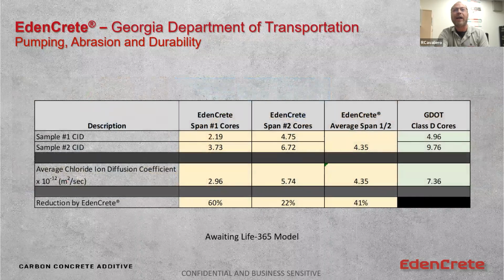We actually went back out, and I just went out with a group a couple months ago, and we pulled cores. We ran that chloride ion diffusion test. And what we're seeing is that with EdenCrete, we had 2 spans, and we have an average of 4.35, but ultimately, we see that 1 span did really well and has a 60% improvement over the reference, which is the GDOT Class D. The second one has a 22% improvement. So when we average that, we have a 41% improvement in permeability over the reference for a bridge deck that's reinforced with structural steel, right?